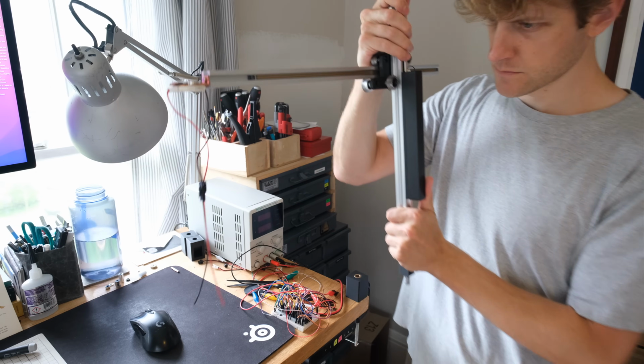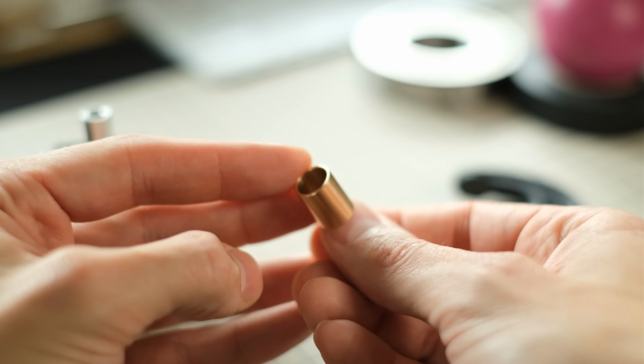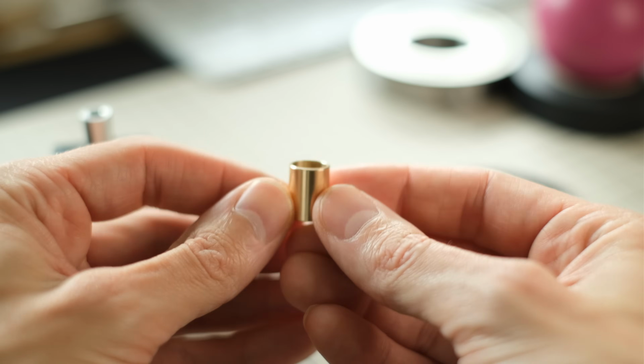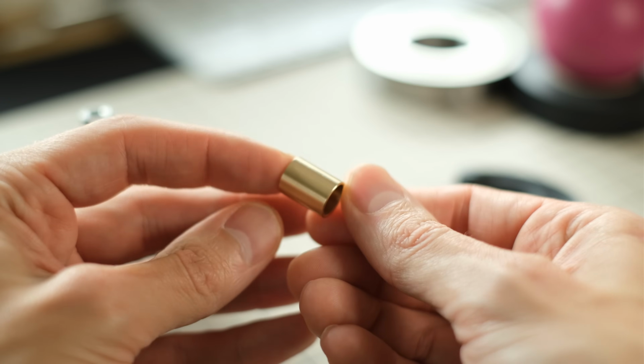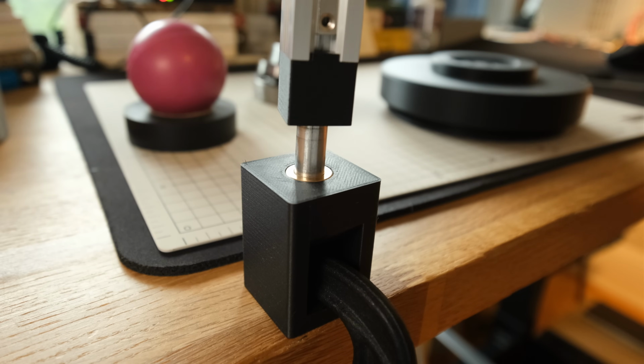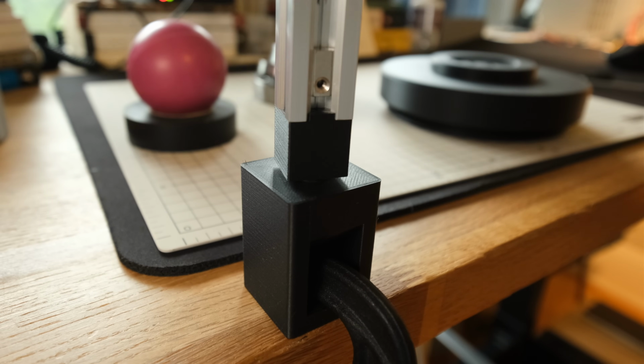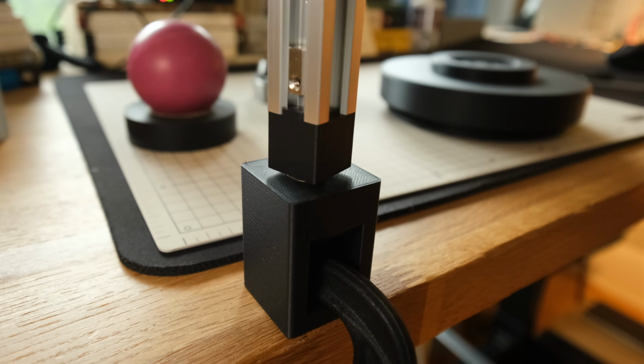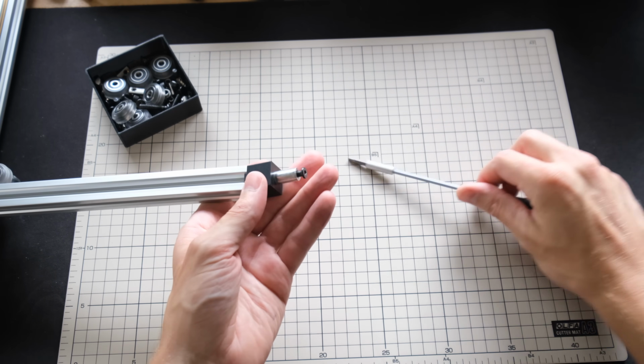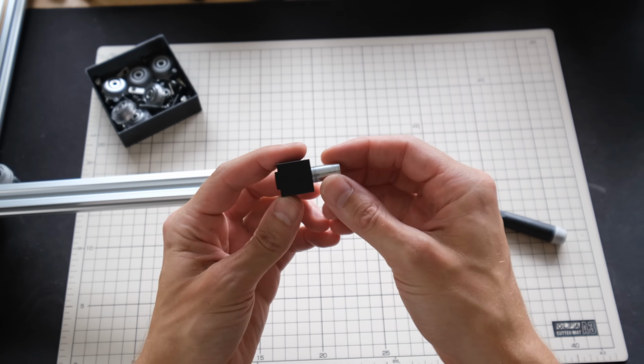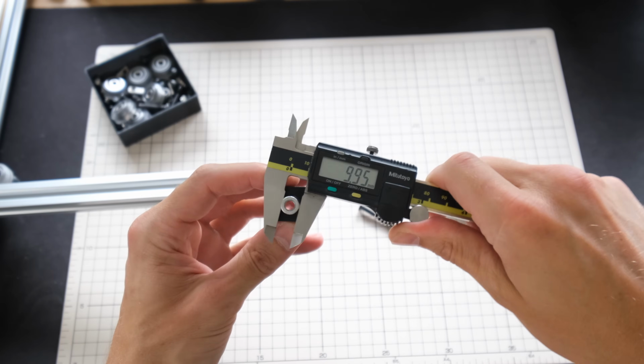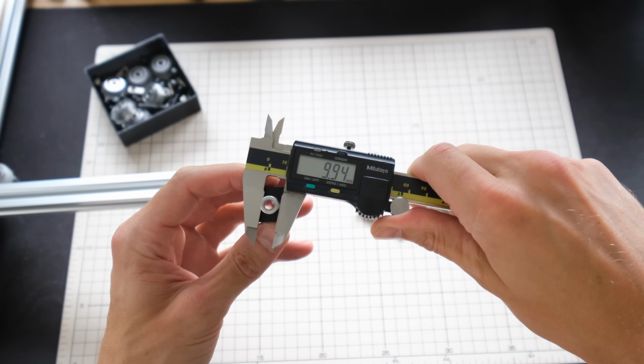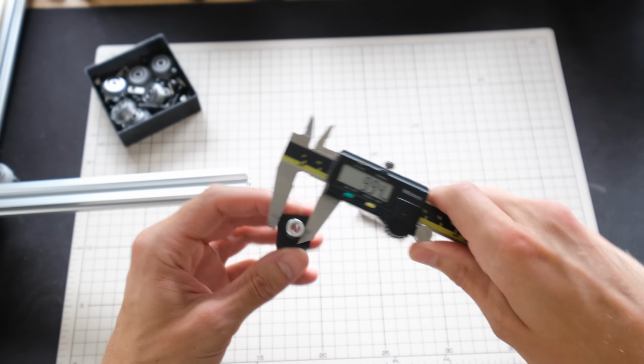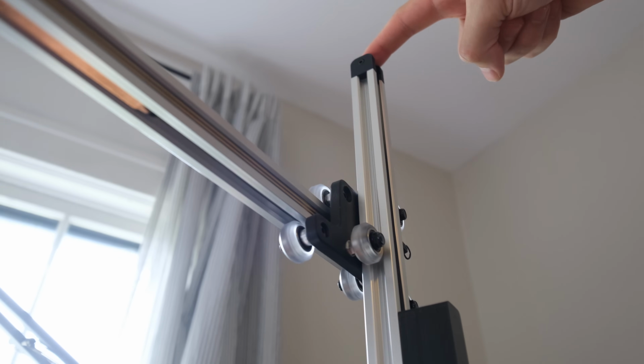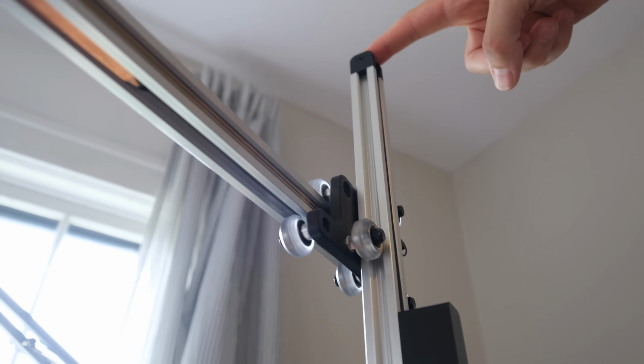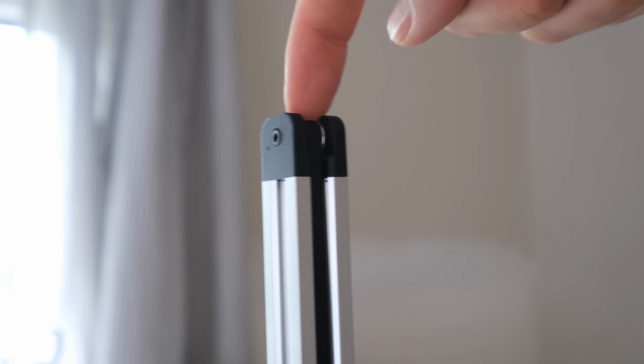First, there's an issue with the clamping base from the last build log. I showed off this really beautiful bronze sleeve bearing that I was hoping to use with the clamping base, and the intent was to pair this with a cheap aluminum spacer for a precise fit, smooth rotation, and minimal wobble. Unfortunately, while the outer diameter of the spacer matches the 10mm inner diameter of the sleeve bearing on paper, in reality, the spacer ends up being closer to 9.94mm, and I think this 0.06mm discrepancy amplified over the height of the lamp is the primary driver of the wobble.